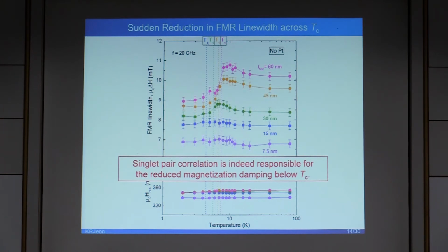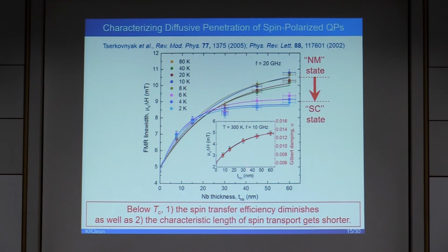To quantitatively characterize this, we have plotted the obtained FMR line width as a function of niobium thickness for different constant temperatures varying from 80 down to 2 Kelvin. For all temperatures, the FMR line width varied with the niobium thickness in an approximately exponential pattern, as expected from spin pumping and diffusive transport. However, when temperature is below 8 Kelvin, the FMR line width saturates faster to a relatively small asymptotic value as compared to the normal state. This means that below Tc, the spin transport efficiency diminished, and the characteristic length of spin transport in the niobium layer becomes shorter.